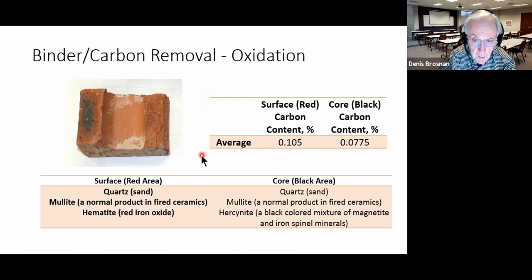same. If you look at the mineralogy of the product, the red areas, quartz and mullite and hematite, red iron oxide, Fe2O3. So if you chisel out the core area, you can find mullite. Well, that's what we expect, but now we found a different spinel called hercynite. Hercynite is a black colored mixture of magnetite and iron spinel minerals. And so this is not carbon right here. It's the effect of carbon reducing the iron oxide to magnetic iron oxide or magnetite, which in firing a brick becomes part of this complex spinel called hercynite.